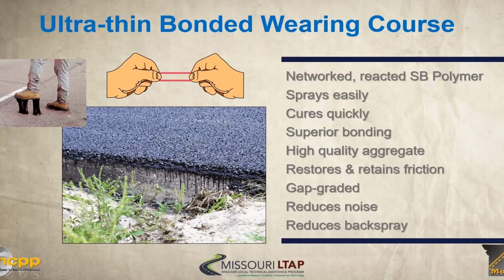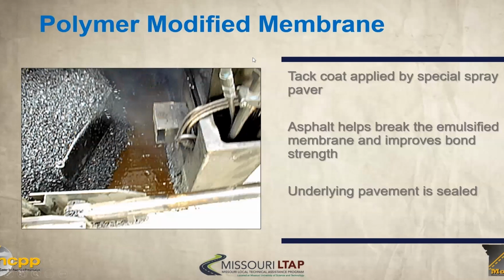This is a picture that I took back in 2001, and you can see this material kind of wicking over a concrete pavement. And I would equate it to the rubber band effect. So it's an SB, styrene butadiene block copolymer. It sprays very easily, cures quickly because the hot asphalt is placed over the top of the emulsion, and obviously has a lot of superior bonding qualities as well. And then you can read the rest. We've got reductions in noise and back spray because it is open graded. It's great on friction. And this is what it looks like when you're looking down at the spray bar in the back of the paver.